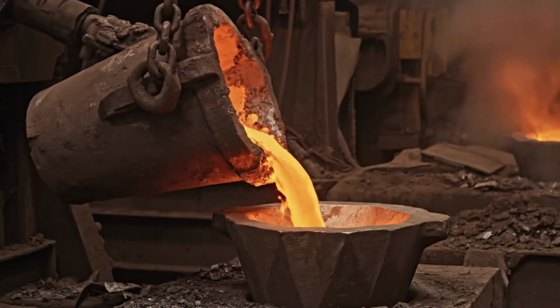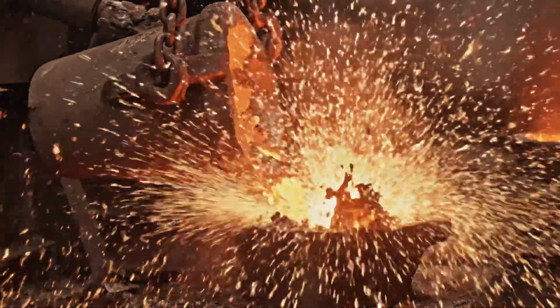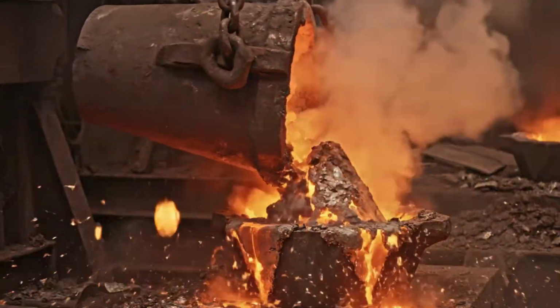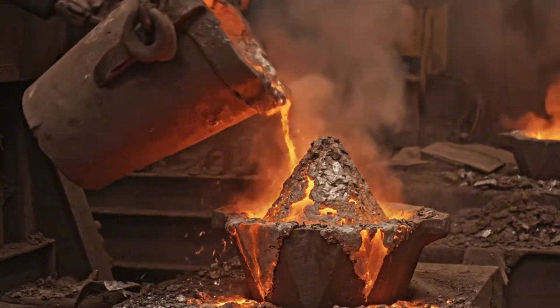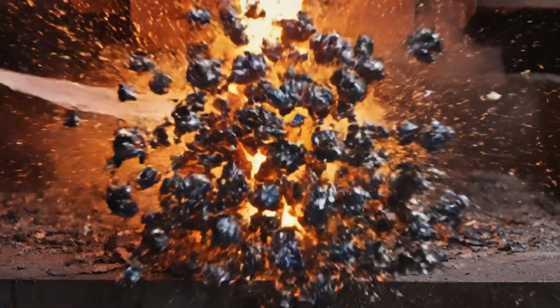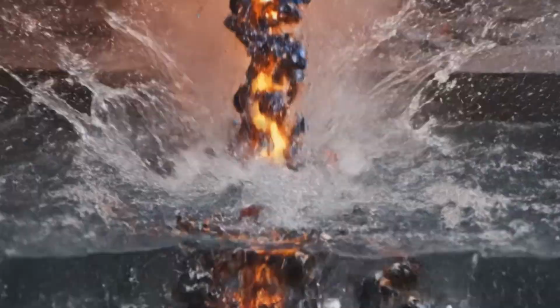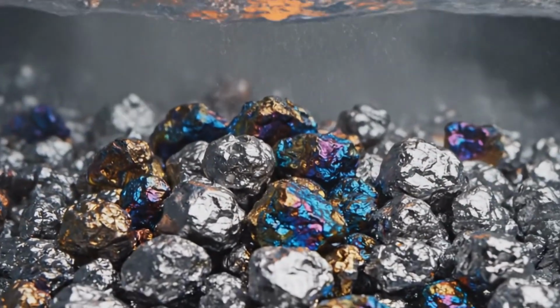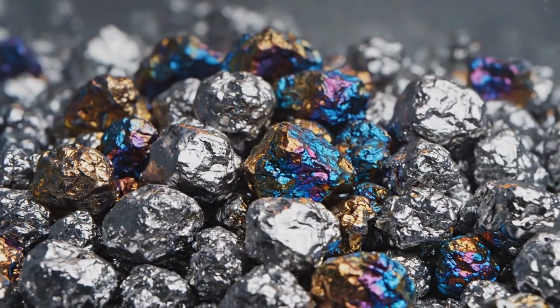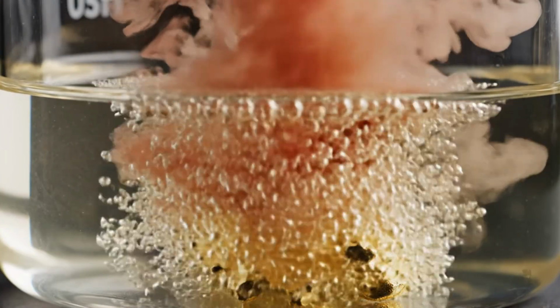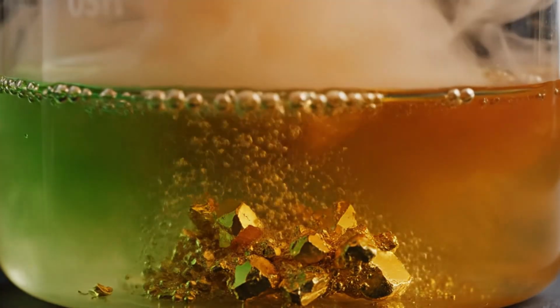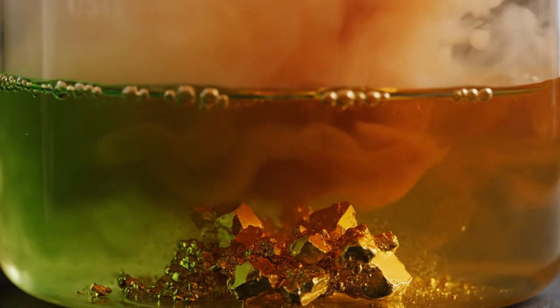We pour this dirty melt into a cone mold, creating a heavy button of unrefined metal that is far from the purity we require here. To separate the gold, we must atomize this button, turning it into small grains that offer more surface area for the aggressive chemical refining process. We introduce these grains to Aqua Regia, a potent mixture of hydrochloric and nitric acid capable of dissolving gold into a vivid orange liquid solution.